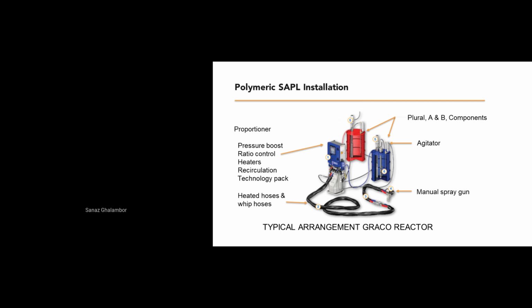That's why we can keep spraying and building thickness without being concerned about sagging, and we don't have to wait between the layers for the tack-free time of the previous layer before we can apply the next layer. It's not like other traditional coatings where we have a window time between the layers, and that's a benefit of the system.